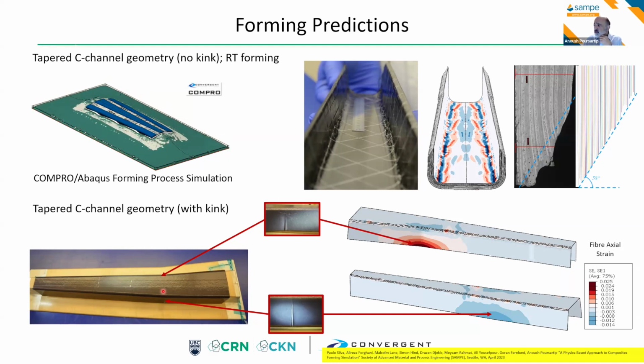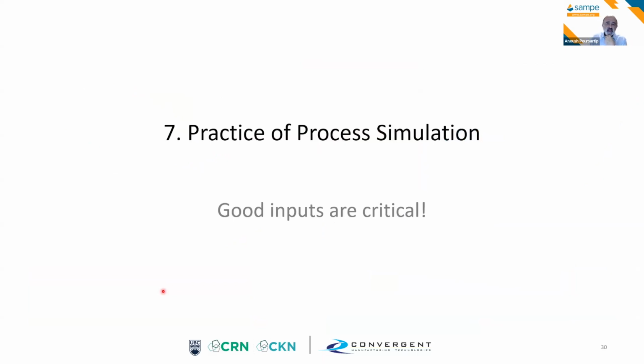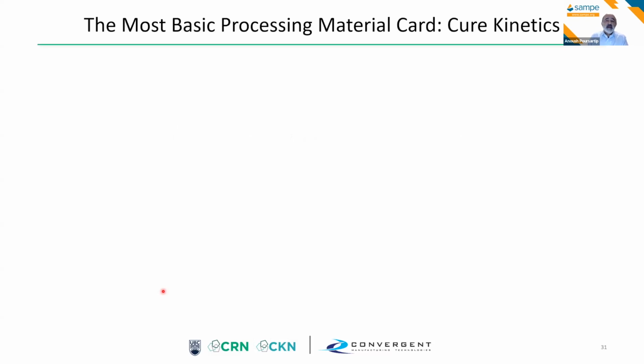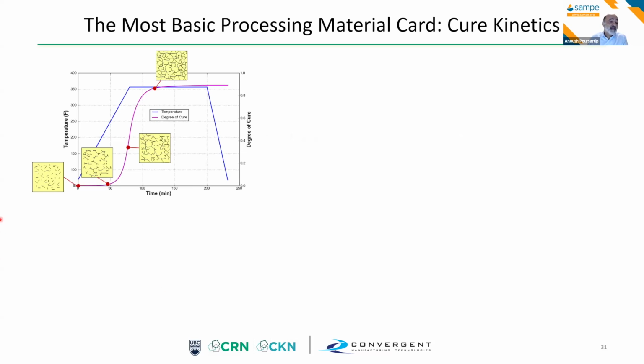Let's move to the practice of process simulation. And the first thing I want to emphasize is that good inputs are critical, even more than if you're doing a structural analysis. The most basic processing material card for a thermoset is the Cure Kinetics model that predicts how the material evolves from a low molecular weight liquid, and as it cross-links, it becomes a gel. Then as the network structure evolves, it actually vitrifies.